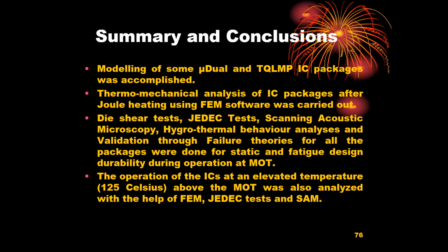Summary and conclusions. Well, we did the modeling of some micro dual and TQLMP IC packages. We did thermomechanical analysis of IC packages after Joule heating using FEM software. We did die shear tests, JEDEC tests, scanning acoustic microscopy tests, and hygrothermal behavior analysis and validation through failure theories for all the packages. We also did static and fatigue design durability tests and analysis during operation at MOT and beyond. The operation of the ICs at an elevated temperature was also analyzed in order to find out where it would start failing above MOT, and whether the criterion of MOT being at least about 25 degrees Celsius lower than the lowest Tg or wet Tg was satisfied or not.